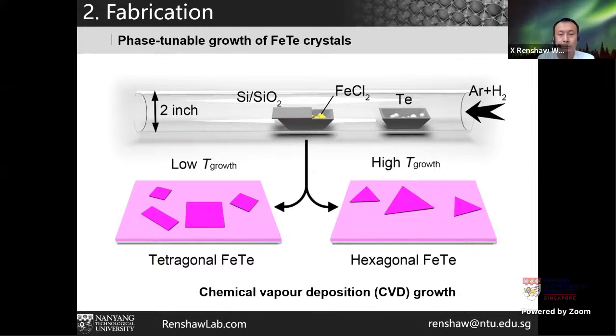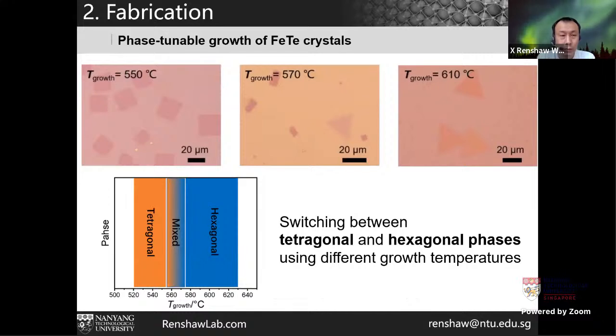Now, to summarize, on the low temperature side, we are able to get the tetragonal phase. On the high temperature side, we are going to get a hexagonal phase. Although it's hexagonal, when we have a flake grown to a certain size, it has a triangular shape. But it's a hexagonal phase, not a triangle. It's a hexagonal lattice, not a triangle lattice. So this is the CVD growth where we played with the temperature.